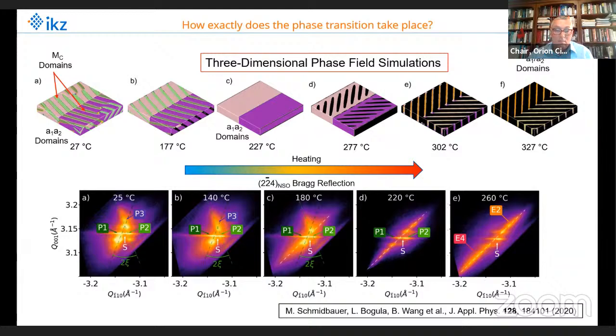But when you go to the middle of this X-ray data at 180 degrees C, you see that only the peaks P1, P2 are preserved, while P3 has vanished. So the MC phase has vanished, and this is exactly what we observe in the simulation. You see here at 227 degrees in the simulation.